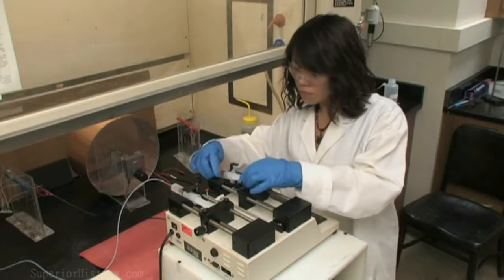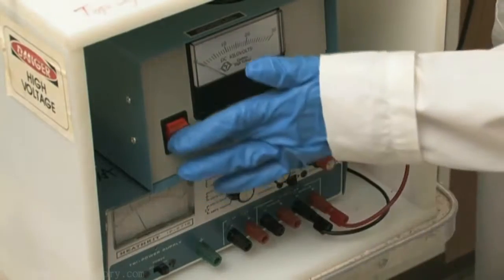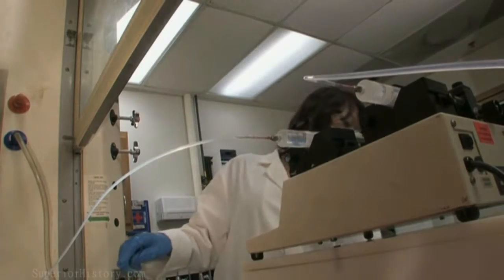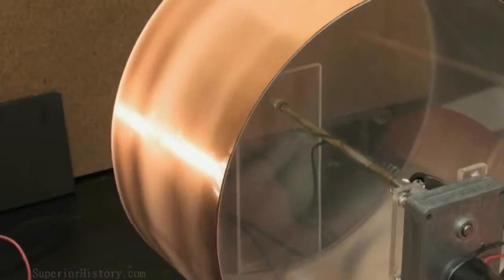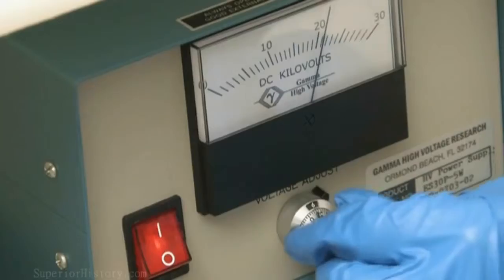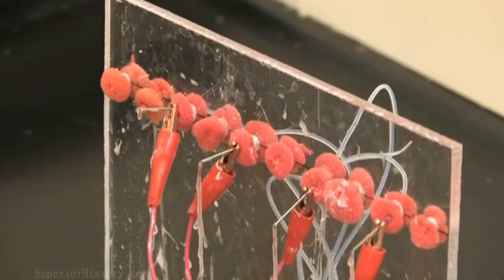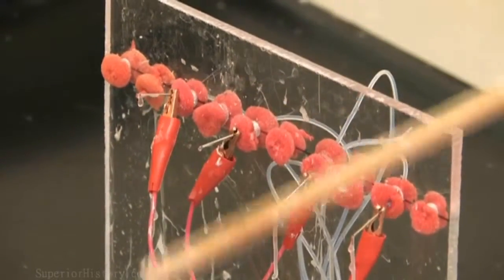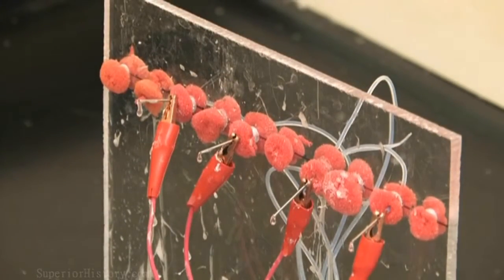With CSR EES funding, Margaret and her Cornell team focused on biohazard detection. The first step was to make the fibers from a time-tested process known as electrospinning. We form a droplet of a polymer solution. We apply high voltage to that droplet, something on the order of 15,000 volts. A very fine jet of polymer will erupt from the surface of that droplet and is collected over on an electrical ground some distance away.